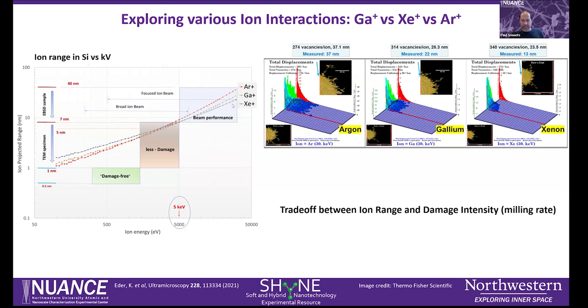But penetration depth isn't the full story. If you look at 30 kV again and compare argon to gallium to xenon, these are simulations that show the amount of vacancies measured in that penetration volume. Xenon actually creates many more vacancies, and this is basically a measure of milling rate. So xenon at 30 kV will preferentially mill larger volumes compared to gallium or argon, even though gallium will penetrate deeper into the material than xenon at 30 kV.